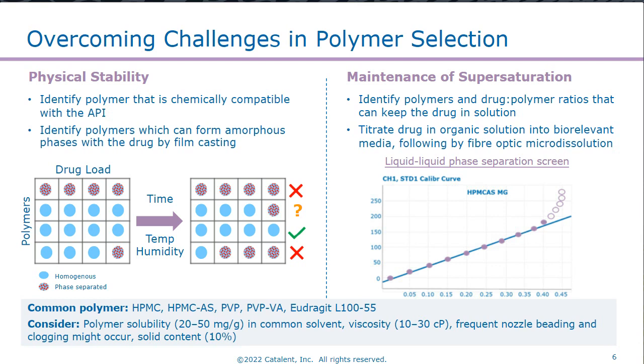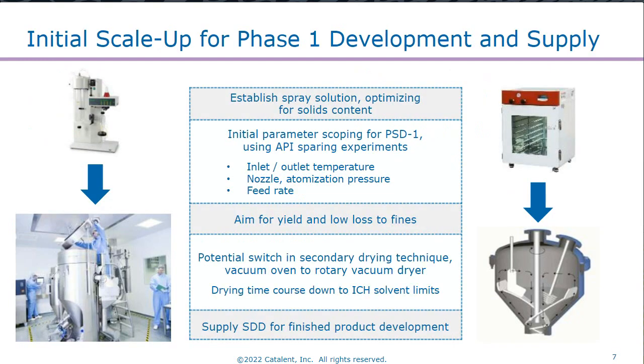And then we're also aiming typically for a total solids content in the solution of around 10%, which will help us with the efficiency of the manufacturing process. So that gives us the initial leads that we would be considering in the lab. So through preparing some of those through small-scale spray drying and characterizing the solid dispersions, we'll select which of the spray dried dispersions we're going to be scaling up for phase 1 clinical supply.